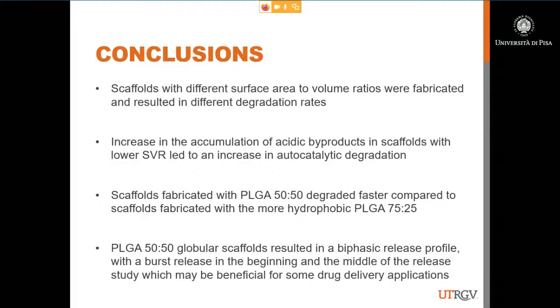So, in conclusion, for this part of our study, we saw that scaffolds with different surface area to volume ratios we were able to fabricate, and they can result in different degradation rates. We saw that the accumulation of the acidic byproducts in scaffolds with lower SVRs led to autocatalytic degradation. And as expected, we saw that scaffolds fabricated with 50-50 degraded faster, and this leads to more drug release over time compared to 75-25. And one of the ones that we saw as interesting was the PLGA 50-50 globular scaffold.